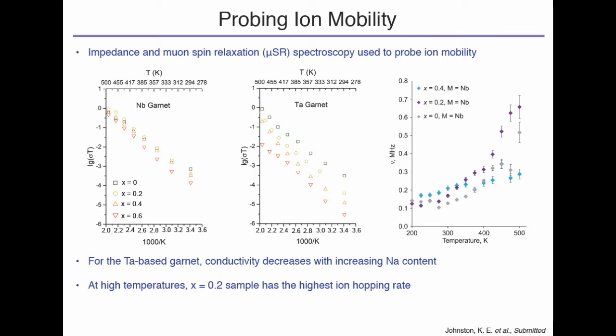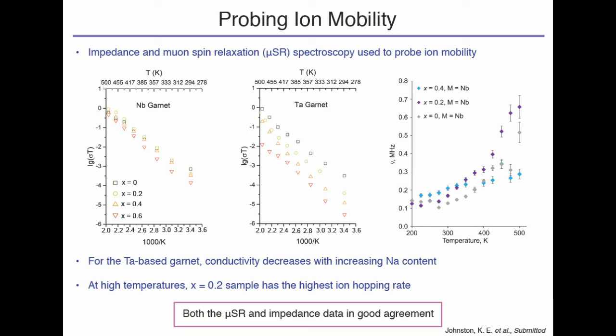Now, we can also do a technique known as μSR, or muon spin relaxation spectroscopy, which is all a little bit complicated, but essentially the muon plants itself into a sample and it can watch for ions moving, and it can plot the ion hopping rate. So this is any ion that is hopping within the system as a function of temperature. The only thing we really need to know about this μSR data is that for this niobium garnet, it basically corroborates exactly what we're seeing in the impedance data. So we see an increase for the 0.2 sample, but the 0.4 sample decreases. So it looks like the more sodium you put in, the more detrimental it is to the system. So why is that? Both the μSR and impedance data are in good agreement.